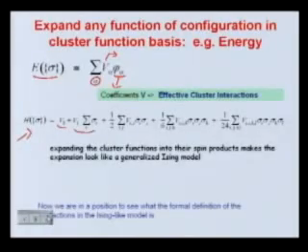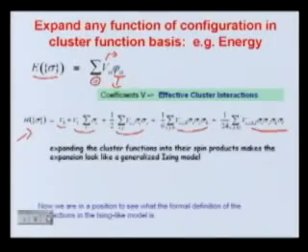So that's this term. When alpha is just a point, you'll have this term. So this is almost like point site energies or chemical potential likes. If alphas are pairs, you'll get the standard pair term that we see in lattice models. But this keeps on going. You'll have triplet terms, quadruplet terms, and so on. So essentially, the cluster expansion is the same as what's called a generalized Ising model, where you go away from relying only on two-body terms to higher body terms as well. It is essentially a generalization of that approach.